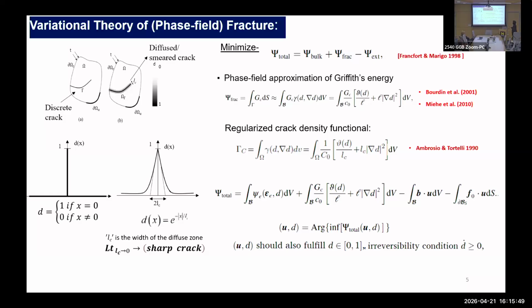Now, in the crack density functional, this gamma depends on both the phase field variable d and its gradient term del d. That gradient controls how sharp the change from d equal to 0 to 1 is going to be, and that control can be done by the choice of your length scale parameter. Okay, so we basically come up with this crack density functional.